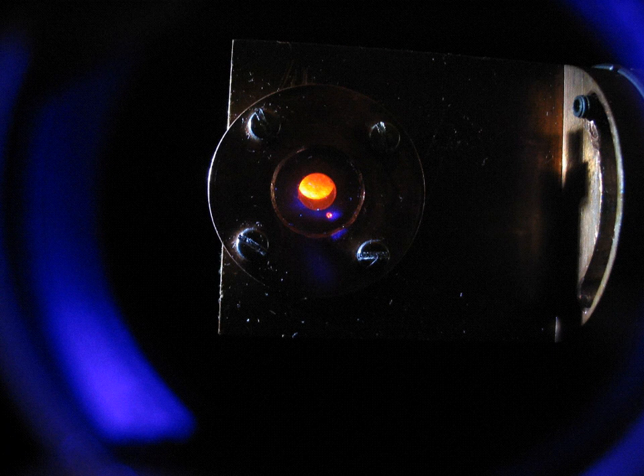Curium is one of the most radioactive isolable elements. Its two most common isotopes 242-Cm and 244-Cm are strong alpha emitters. They have relatively short half-lives of 162.8 days and 18.1 years, and produce as much as 120 W/g and 3 W/g of thermal energy, respectively. Therefore, curium can be used in its common oxide form in radioisotope thermoelectric generators like those in spacecraft. This application has been studied for the 244-Cm isotope, while 242-Cm was abandoned due to its prohibitive price of around US$2,000 per gram. 243-Cm with approximately 30-year half-life and good energy yield of approximately 1.6 W/g could make a suitable fuel, but it produces significant amounts of harmful gamma and beta radiation from radioactive decay products.